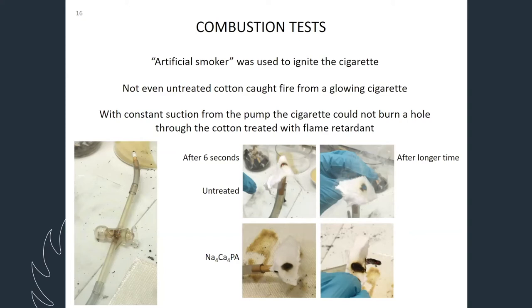And I used a stopcock to control the amount of air suction, because if I connect it to the pump, the cigarette burns in a few seconds. And you can see there are some yellow things, that is sand. So in between the experiments, I extinguish the fire of the cigarette by just dipping it in the sand.